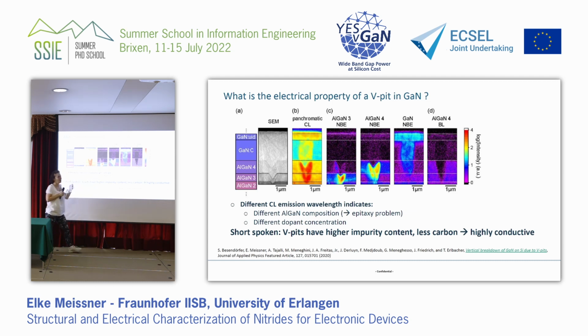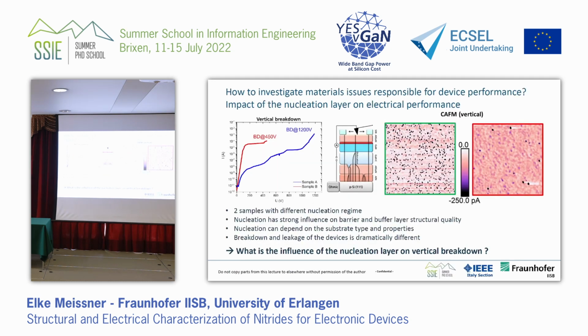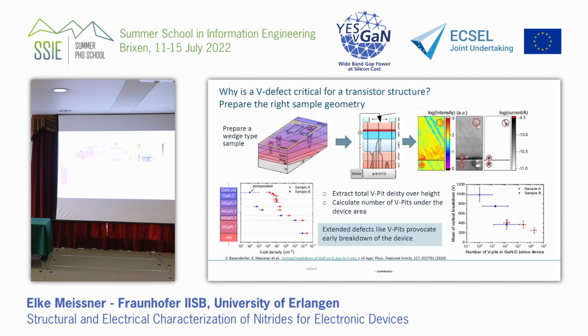We said, okay, this is carbon and oxygen that's going to these V-pits, and carbon and oxygen, if the oxygen goes there, you have an N-type dopant. So they are N-type conductive. So this is what creates leakage. So plainly spoken, the V-pits have a higher impurity content. They have less carbon, as you can see here, and they have a high content of oxygen, so they are highly conductive gallium nitride. And this is what is causing the leakage. And this is why the sample with the 1200 volt has fewer leakage spots, because it has fewer V-pits, not because it has fewer dislocations. So don't be cheated.